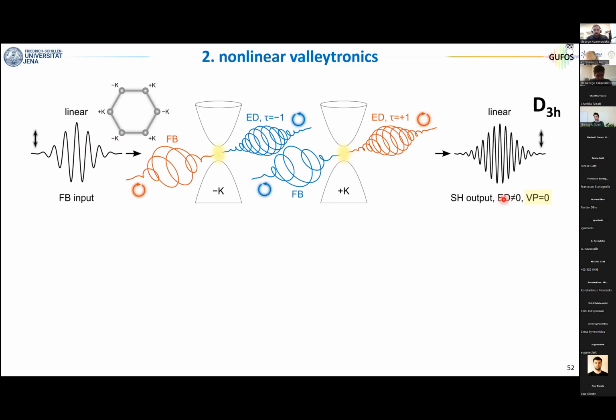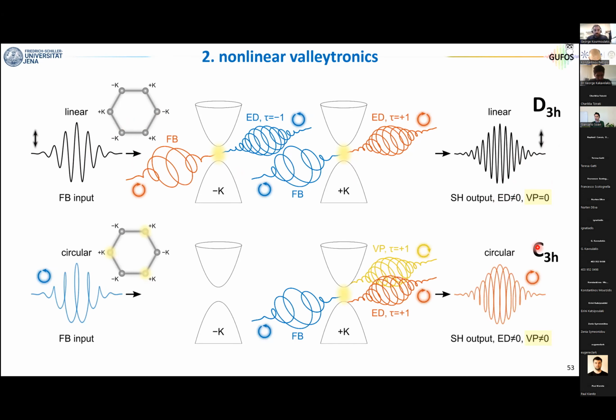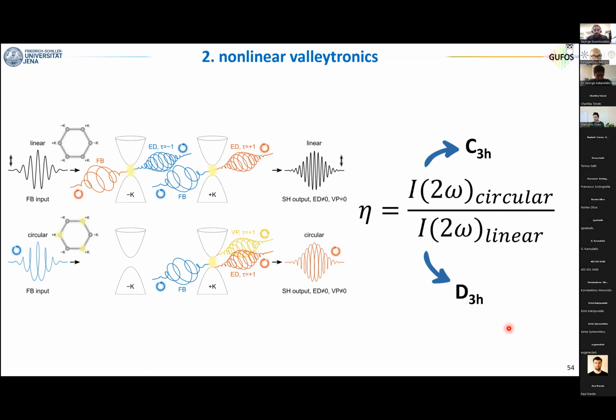In this case, the electric dipole, that is broken space inversion symmetry, gives the second harmonic. The valley polarization, that is time reversal symmetry, is preserved. The system belongs to this D3h point group. If we now shine circularly polarized light, the point group changes because we are breaking time reversal symmetry. Our second harmonic comes not only from the electric dipole, but also from the valley polarization. Now, I want to convince you that if you take the ratio between the intensity when you shine circularly polarized light and the intensity when you shine linearly polarized light, this ratio contains information about the valley polarization and about the broken time reversal symmetry.